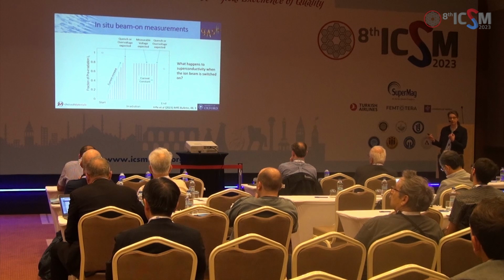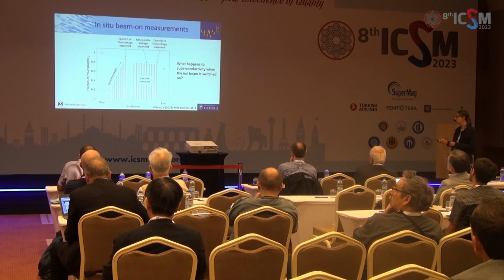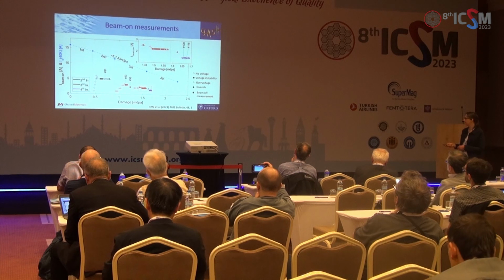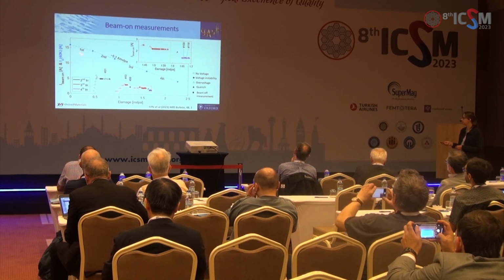And during this, of course, the sample's being irradiated, so we'd expect it to be getting worse, be getting damaged, and so what we'd kind of expected is that we would see no voltage here, and then we'd start seeing a voltage as the damage comes in. What we actually saw is something like this. Now, this is a complicated diagram. It's damage as a function of various things here.